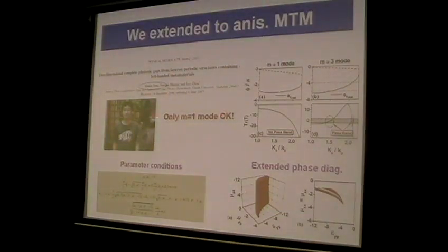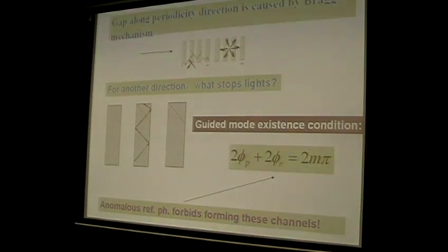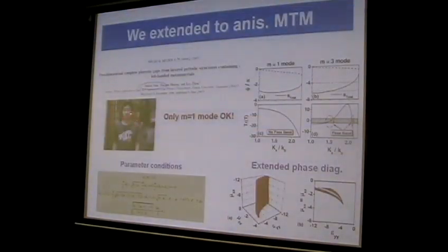2 years ago, we extended the idea to anisotropic metamaterials. In the previous Australian group's work, they proposed the system to be composed of isotropic negative index material. However, isotropic material is very difficult to fabricate. And my student, Shu Ying, extended the idea to anisotropic material. We found some interesting physics. First, only the m equals 1 mode is okay to open this complete bandgap. And he also found very complicated parameter conditions for this anisotropic material. Because we have more freedom to choose parameters, we can have a more extended phase diagram to support this complete bandgap.